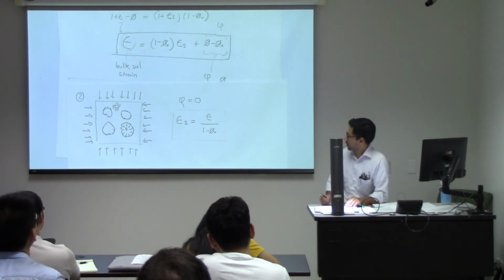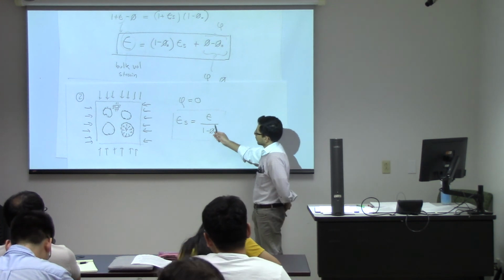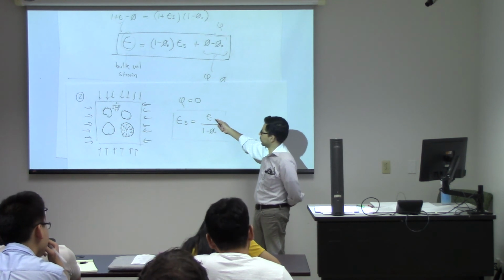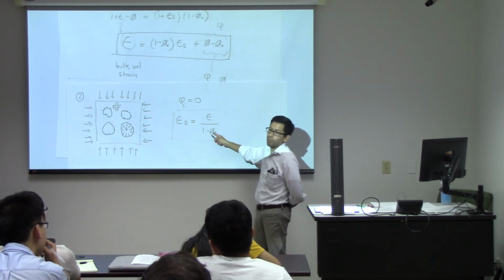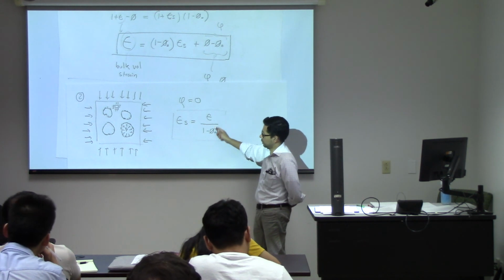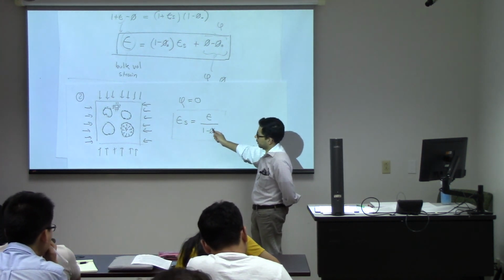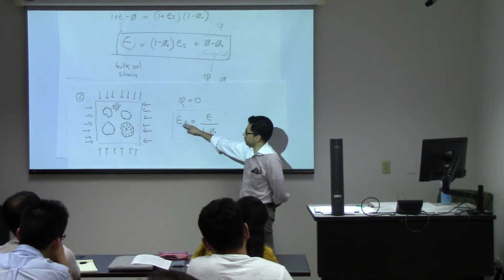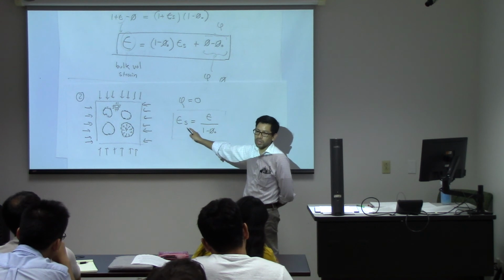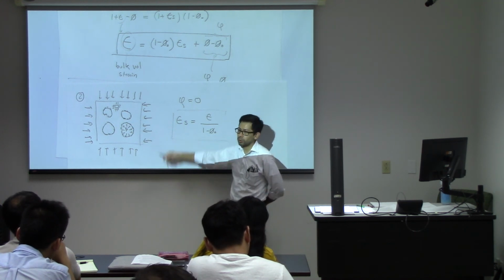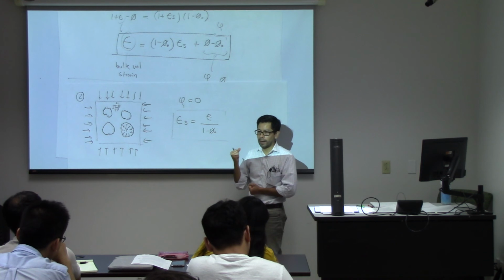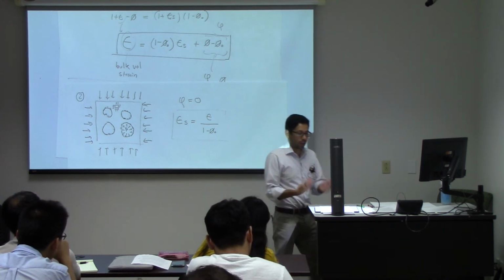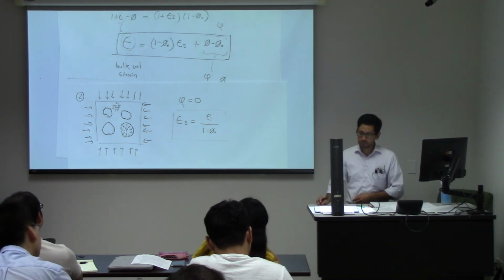And also very interesting in that is, for example, say that here you have a strain of 10% and you have a porosity of 0.5. That means that in order to keep the pores of the same size, the strain of your solid will have to be 20%. So your solid will shrink 20%, but the porous solid is just going to shrink 10% because it's a combination of the two.